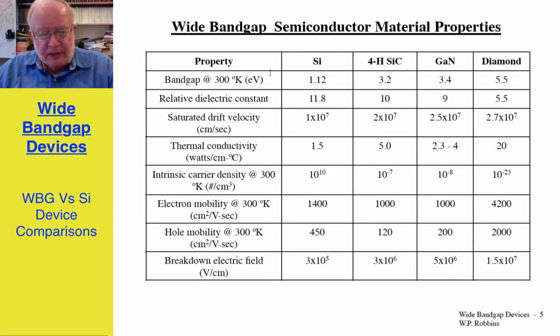The reason for the interest in these wide bandgap materials is summarized in this table of material properties. I list four materials, including silicon carbide, gallium nitride, and diamond. Bandgap. Wide bandgap materials have significantly higher bandgaps than silicon: 3.2 for silicon carbide, 3.4 for gallium nitride, and 5.5 for diamond. I list the relative dielectric constants, and they're similar. Diamond is about a factor of 2 smaller. Their saturated electron drift velocities are similar, diamond having the highest saturated drift velocity.